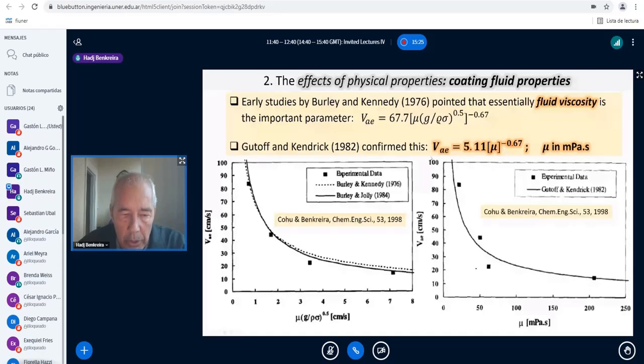And the net result, when you look at all the data, is that viscosity is the important parameter. And you will understand later on why the viscosity is very important. And you see in here, in the range of viscosity, say between 50 to 250, you can almost quadruple the air entrainment speed. So at about 250 millipascal second, the air entrainment speed would be just slightly above 0.2 meter per second. But then if you decrease your viscosity to about 10 millipascal second, then you will be able to coat in excess of 1 meter per second.